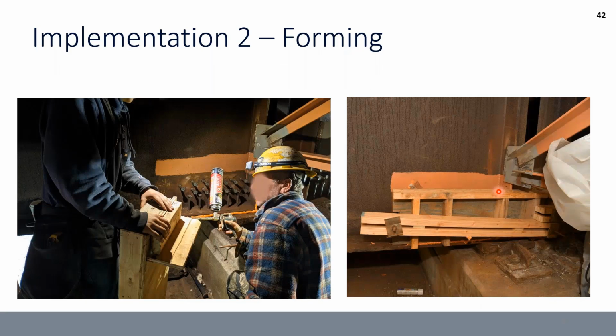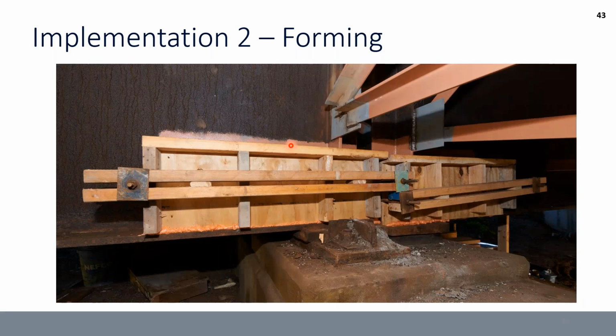Forming was certainly much easier for the partial height repair. And one of the interesting things that you'll see here is for the partial height, this project also included replacement of some of those diaphragms, and those were lifted above the limits for the UHPC panel to prevent encasing any of the steel if future repairs were required. But otherwise, very similar forming with the plywood. We went with the same hole drilled through the back of the web, and then another rod going through the place between the gap and the webs of the beam on the same pier.